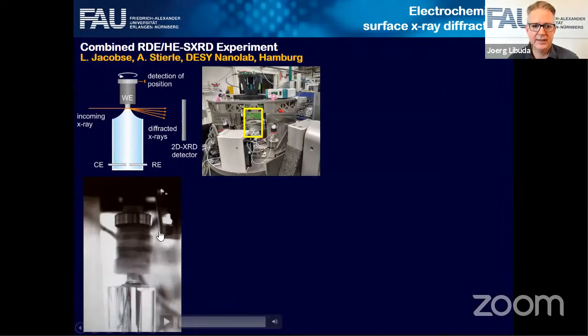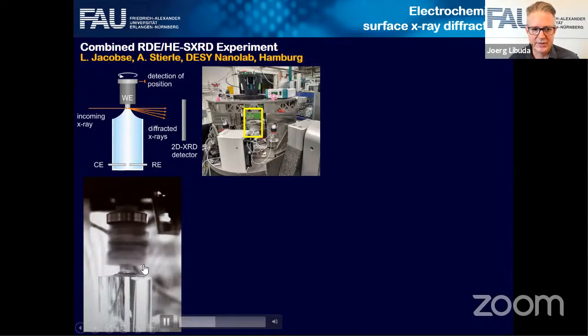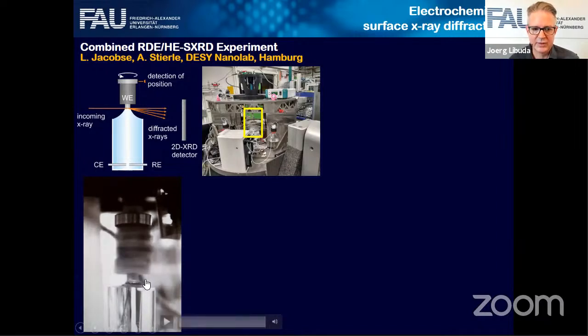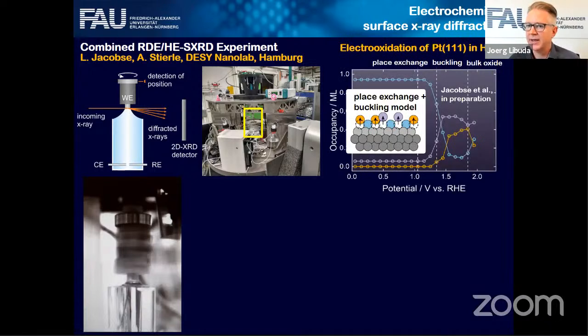And this is an example here of a surface X-ray diffraction experiment in the group of Andreas Stierle at DESY. That is combined with a rotating disk electrode. So there is a single crystal here, it's rotating. There's a meniscus formed to the electrolyte, and then you can reflect your X-ray beam from this interface. And of course, the detector has to be synchronized with the rotation. But with 2D detectors, this is all possible, and you can extract structural information right under reaction conditions. So this is a very beautiful diffraction experiment suitable for such model systems.